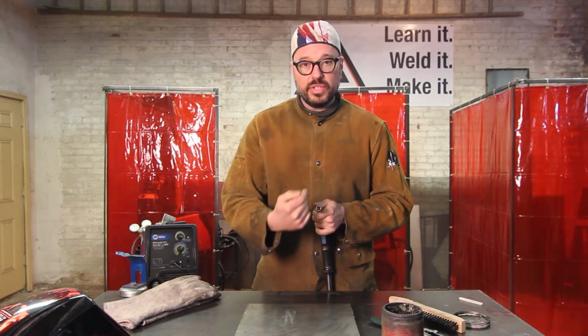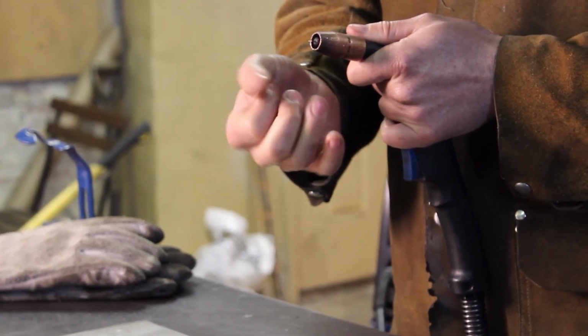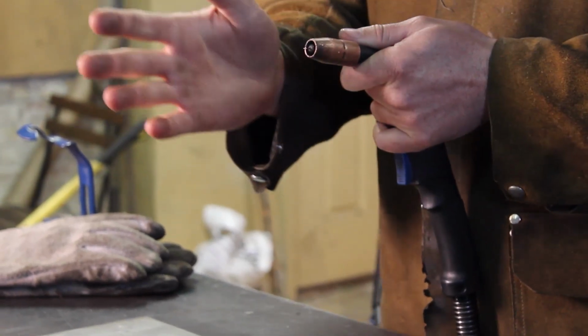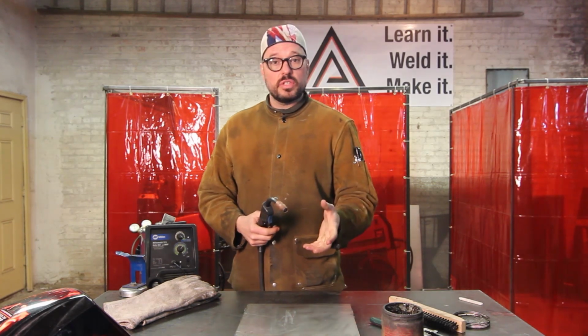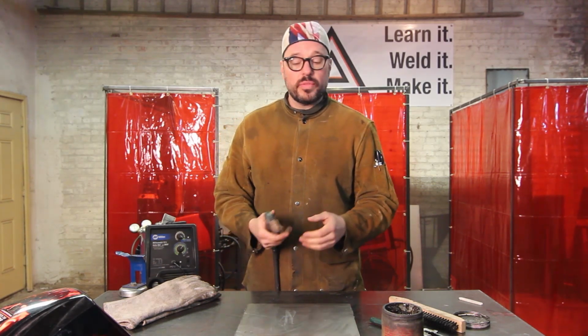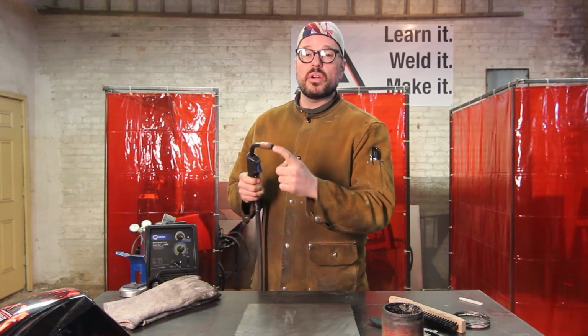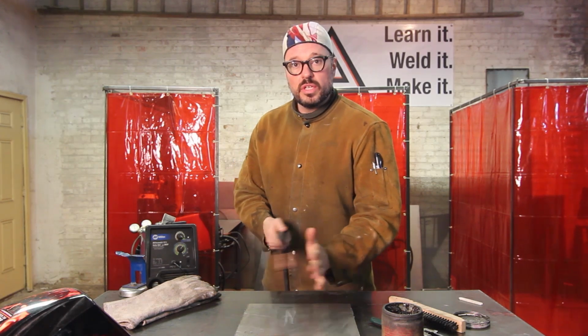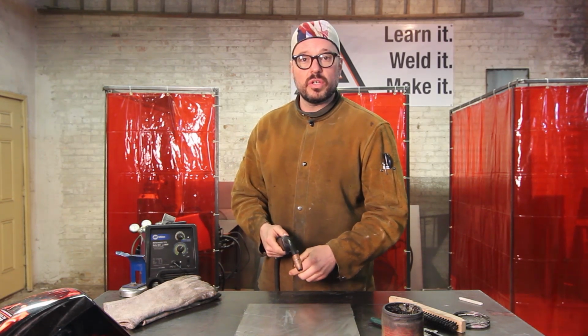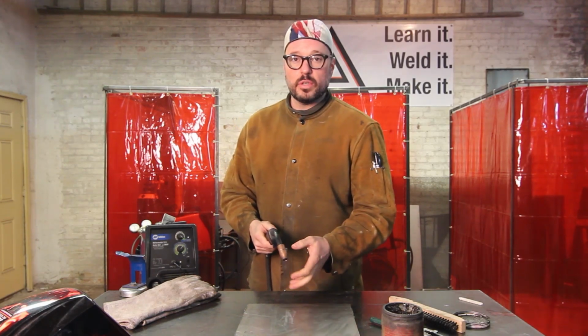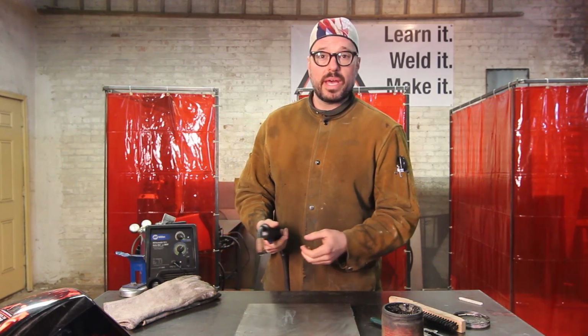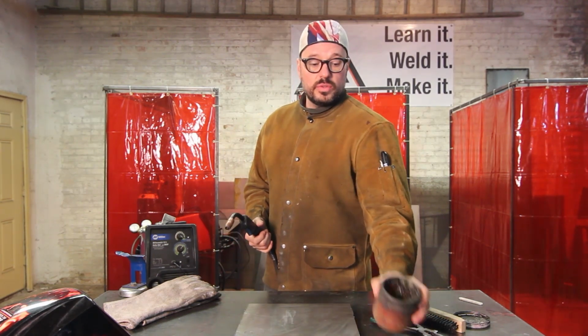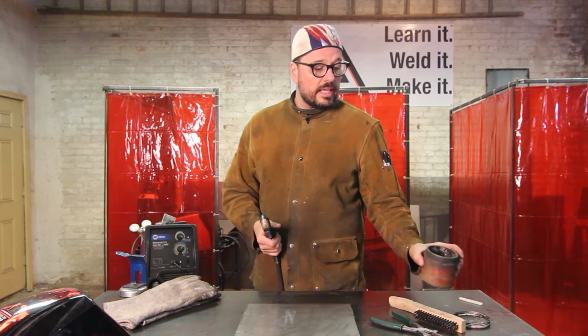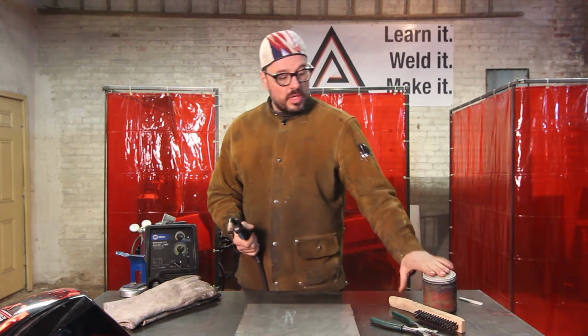Another reason, buildup reduces your shield gas port. The face of where your shield gas is coming out, it reduces that. So you reduce your shield gas, it becomes turbulent, and you get poor welding. So that's also something to consider. If you build up enough spatter on the inside as well, as you're moving through the weld zone you accidentally knock this, it falls into your weld zone, and you've got contaminated steel falling into your puddle, again leading to bad welding. So try to avoid all that. Use this stuff, it's great, it works, I highly recommend it. Okay, so that's tip dip.